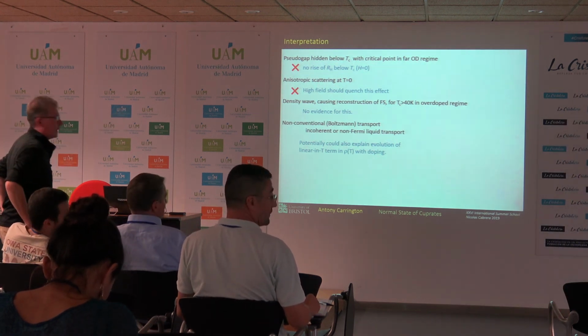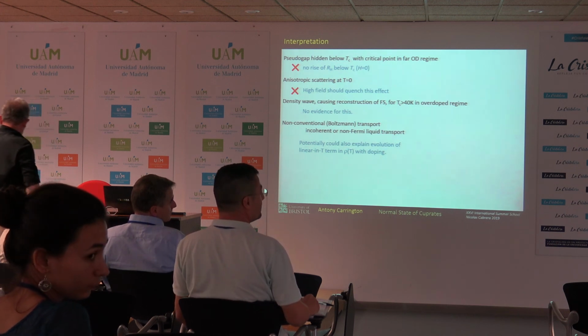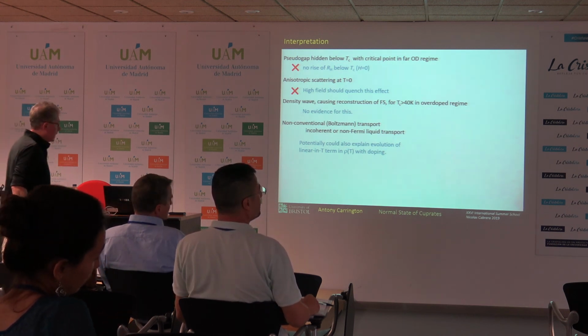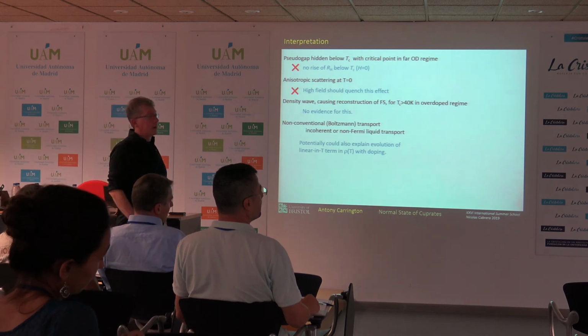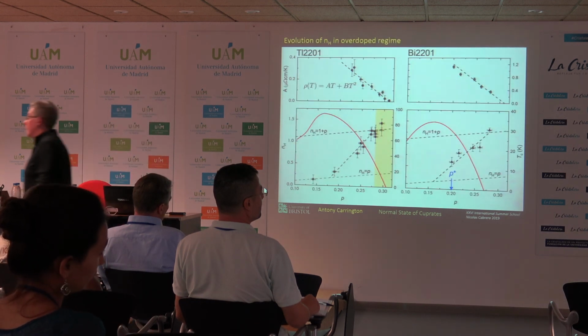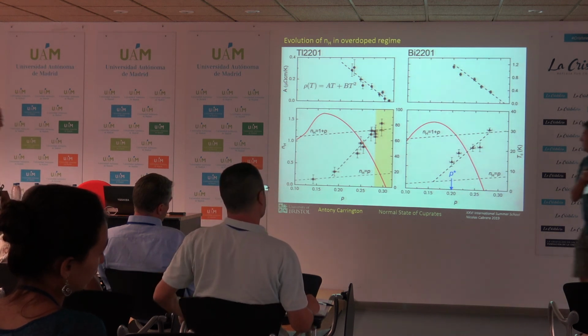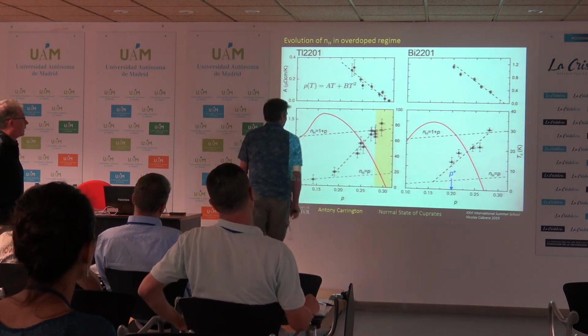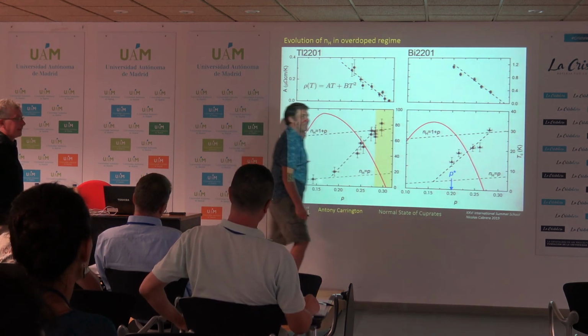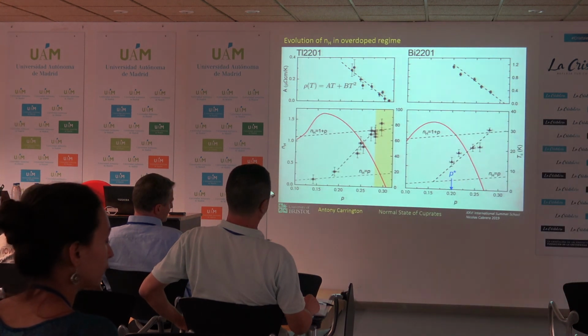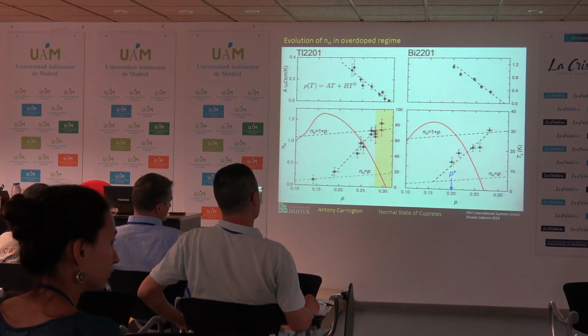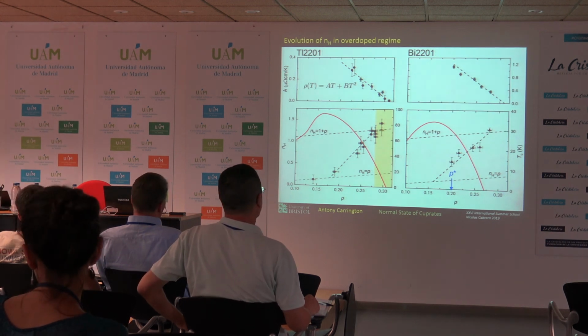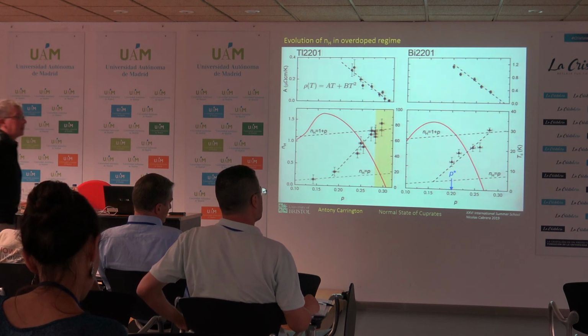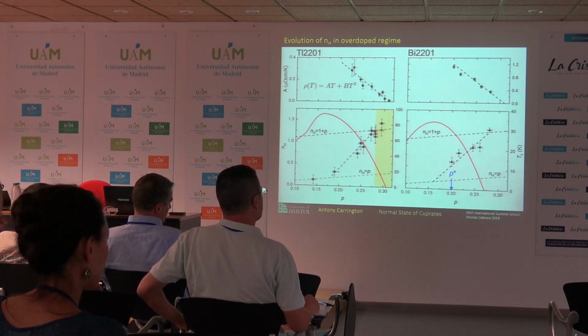Okay, great. If I got the statement the right way around, the correction that you're proposing we need to take for the YBCO Hall data would bring that YBCO data down further? I didn't put it on because it's a bit incendiary, but if you did, the YBCO data sits on that one. But the problem with YBCO is that you don't actually know what that ratio is. You know it's around 1.5 at a certain doping, but no one's really done a systematic study to show what that is at low enough temperature in high field. But it's a substantial correction anyway. It's not inconsistent.